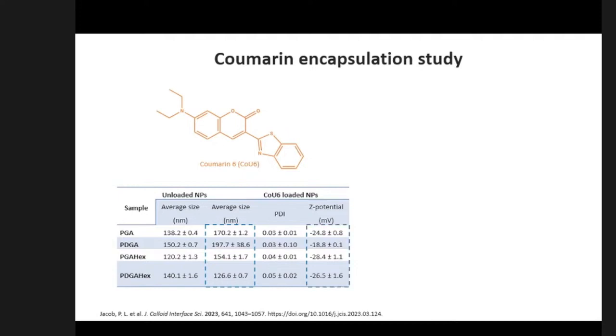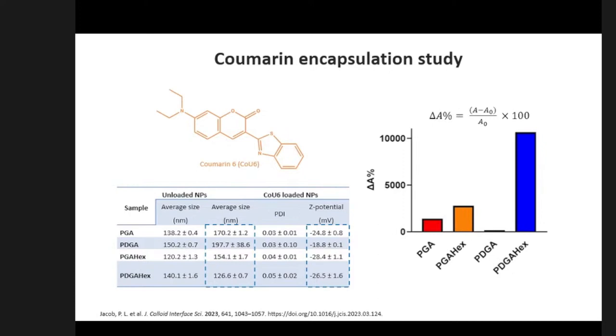And the apparent solubility of coumarin-6 was measured by UV-Vis and calculated using this equation. And all the polymeric nanoparticles were ranked according to the delta A percentage value. Hexandiol-based polymers showed an increase in the apparent solubility of coumarin-6, which was especially higher for PDGAHex nanoparticles.